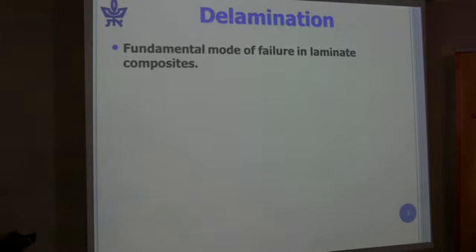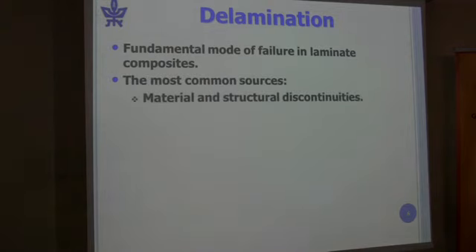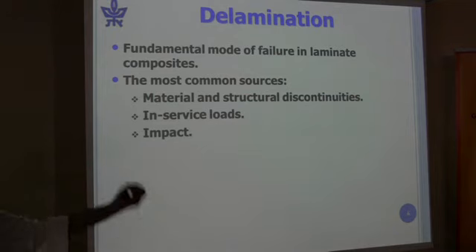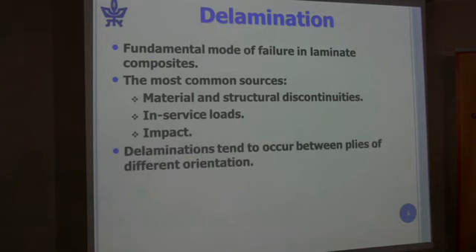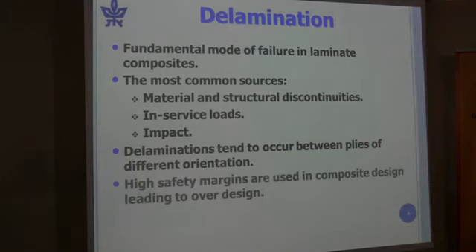It's a fundamental mode of failure, and the common sources are material and structural discontinuities, in-service loads, and in particular impact. A plane is flying along, moving along the ground, and a stone hits the wing, and it impacts it, and it causes separation of the layers. It's very common, unfortunately. And so the delaminations tend to occur between plies of different orientations.